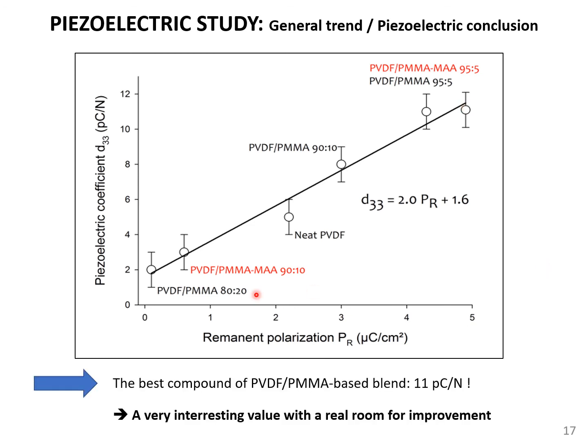This is the best result that we obtain without any annealing afterwards, indicating that our approach is quite solid by comparison with other approaches based on stretching or based on copolymerization.